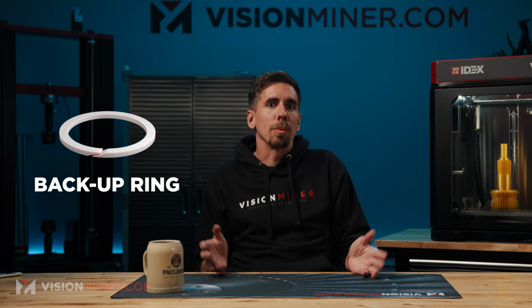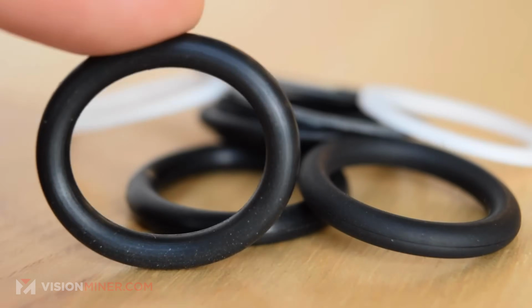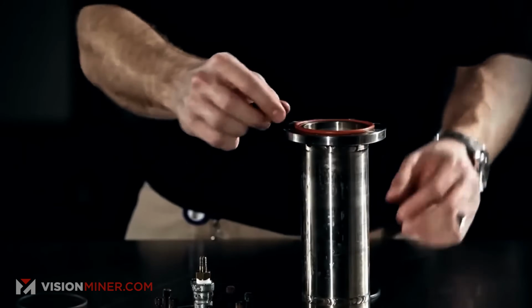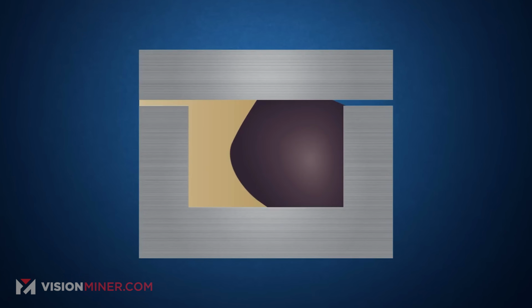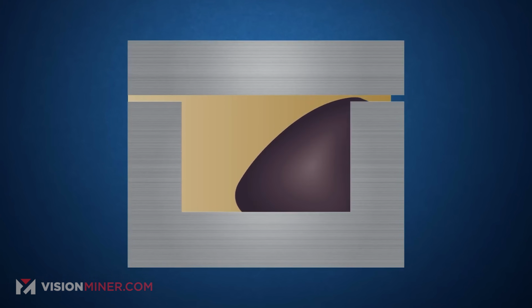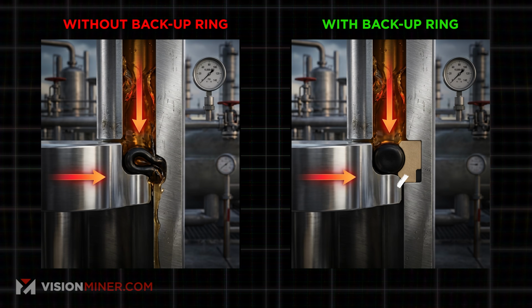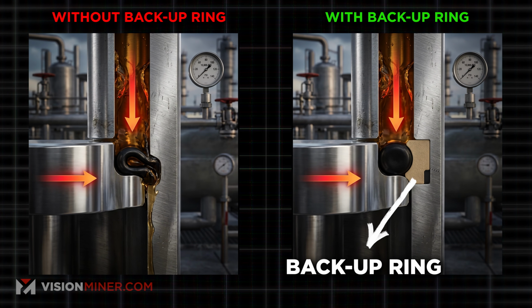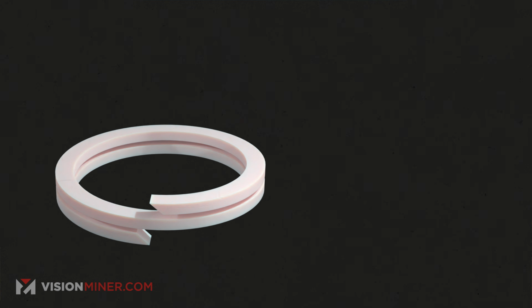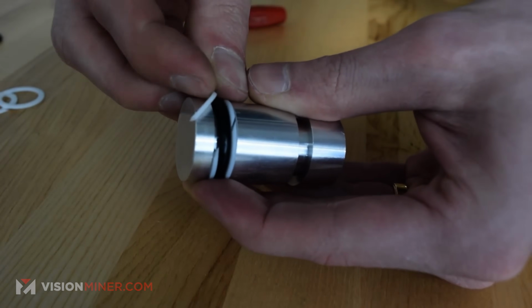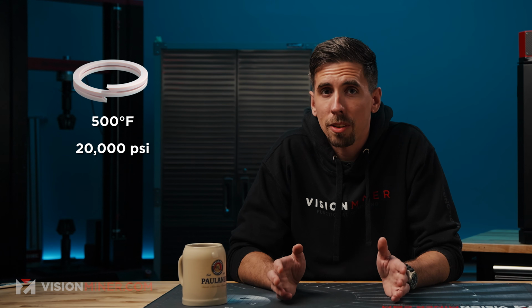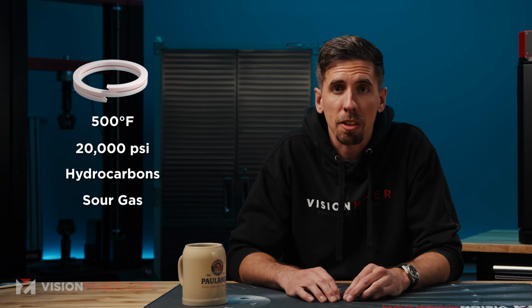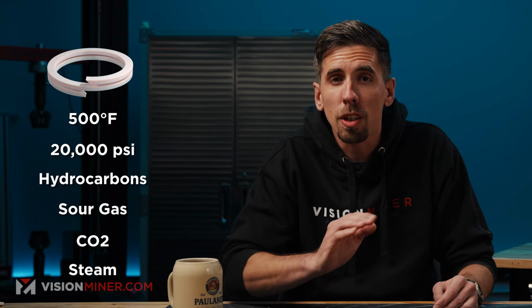So let's back up a little bit. What is a backup ring? In a high pressure assembly, the seal is usually a rubber O-ring. If you squeeze it hard enough, it oozes into the clearance gap between the metal parts and the seal goes bad. A backup ring blocks that gap. For HPHT service, high pressure, high temperature service, PEEK has been the default for these rings for decades now. 500 degrees Fahrenheit, 20,000 psi, hydrocarbons, sour gas, CO2, steam, all of the elements.